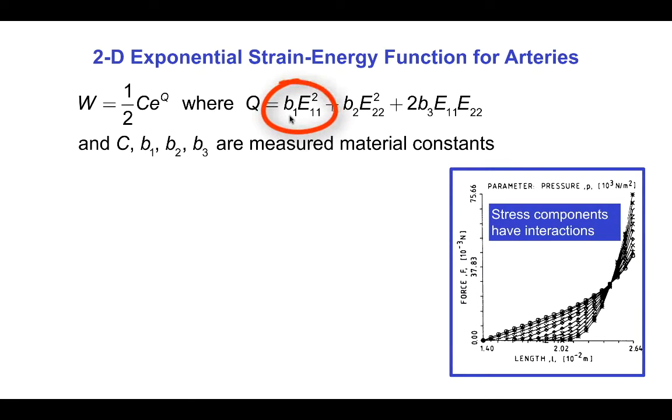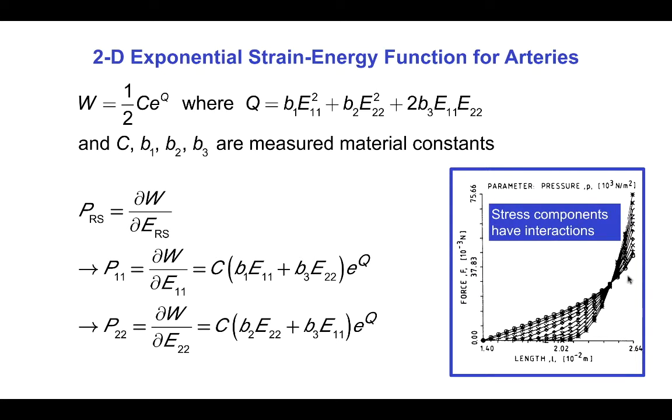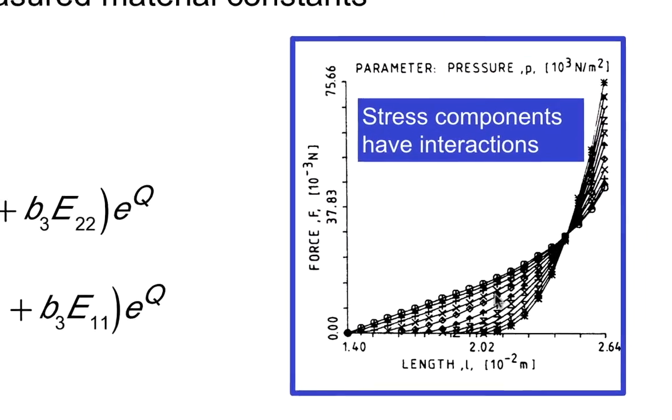B1 here determines the uniaxial properties in the x1 direction, B2 determines the uniaxial properties in the x2 direction, and B3 determines the interactions between the x1 and x2 directions, i.e. the effects of E22 on T11 and the effects of E11 on T22. This allows for the kind of complex nonlinear interactions between strain in two directions, as seen here, for example, in